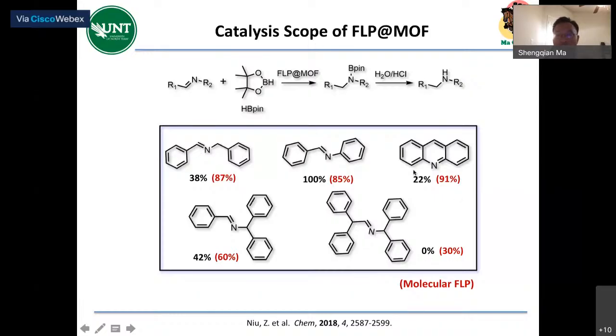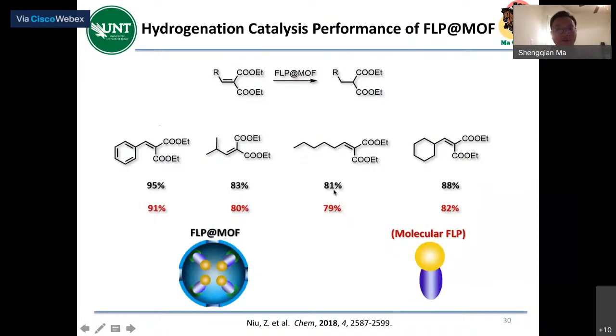That causes this so-called very interesting steric selective hydrogenation reaction. Of course, here we use the pinacol borane, the boron hydride. Of course, we want to do the hydrogenation reaction. We also demonstrate we can use hydrogen to reduce this double bond. And also it's comparable or even slightly better than a homogeneous system. That's because of the local confinement effect of the MOF, because the substrate concentration and also the reactant in the MOF nanospace is much higher than in the homogeneous solution.